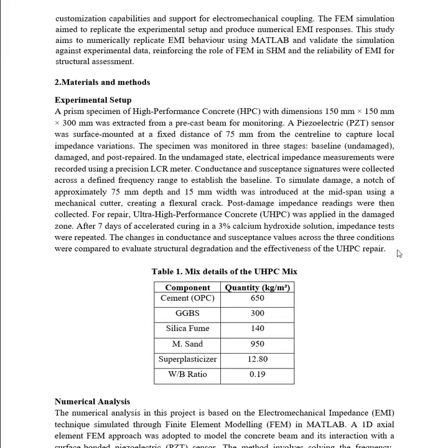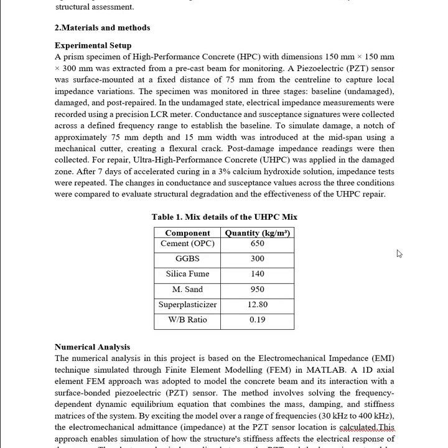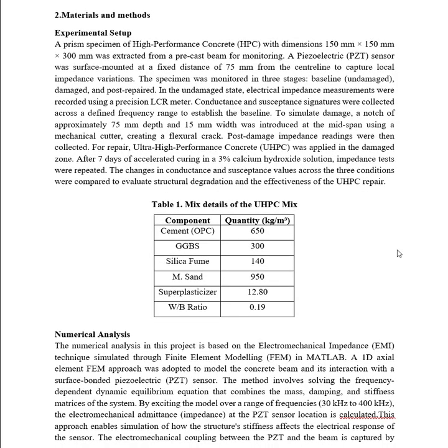Now let me explain the experimental setup which I have considered for this project. I prepared a prism specimen of size 150 by 150 by 300 mm from a precast HPC beam. The PZT patch was bonded 75 mm off the center line, and EMI responses were measured in 3 stages, which I mentioned already.